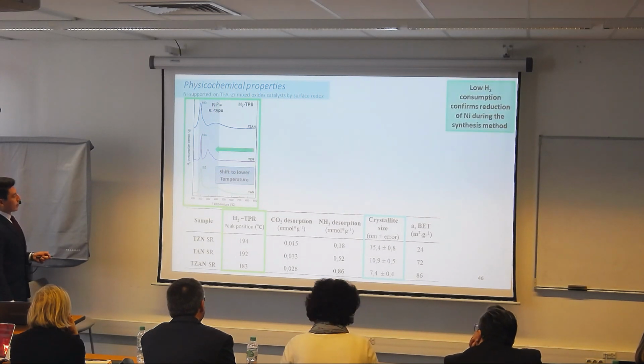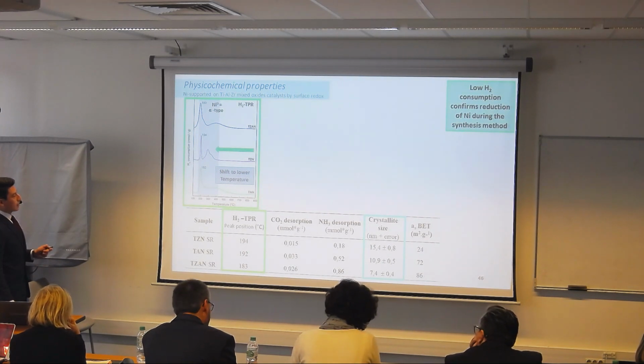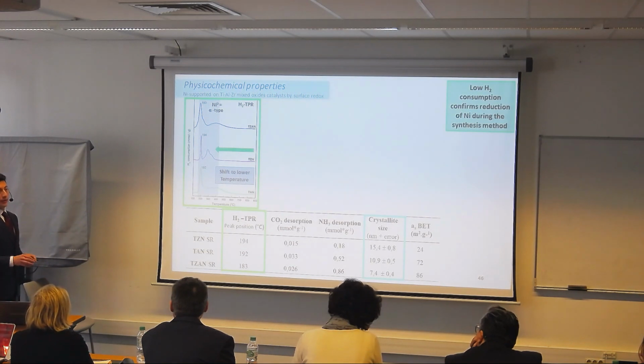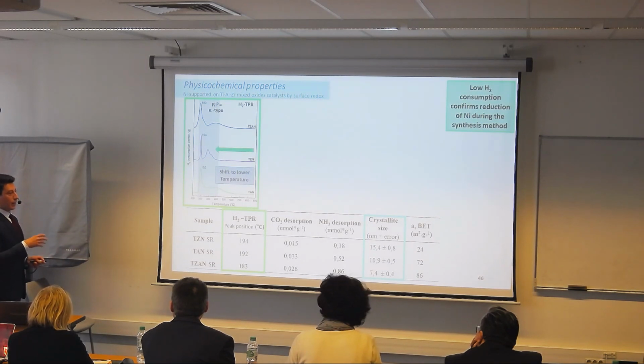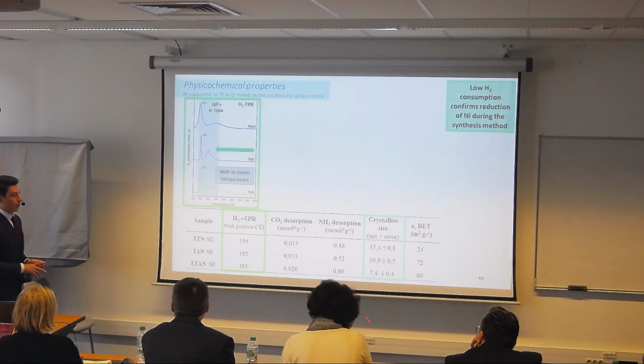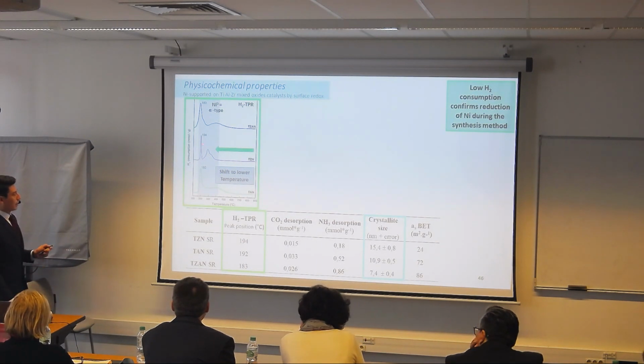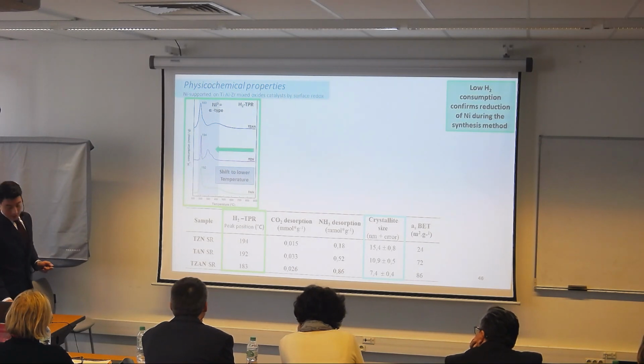In the beginning, we can see that the reduction temperature is very low, and this is correlated to the nature of this method. The deposition of nickel happens in a hydrogen atmosphere, so the nickel deposited onto the support is already reduced after the synthesis. These peaks are just the remaining species of nickel on the surface.